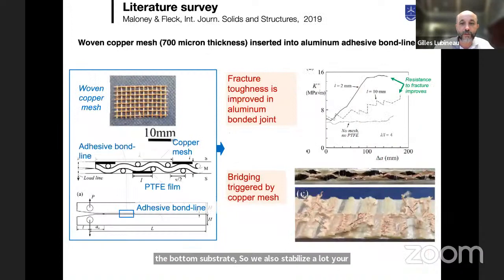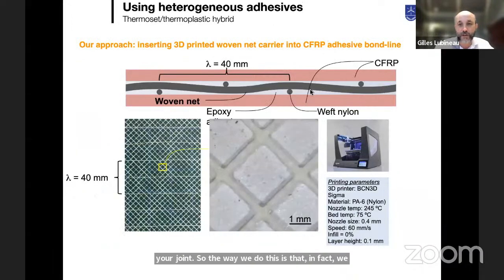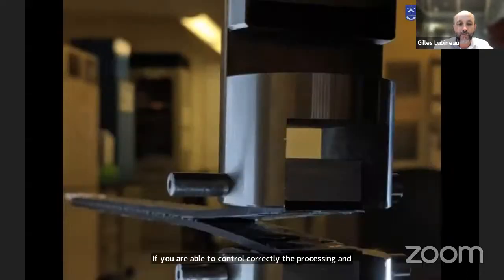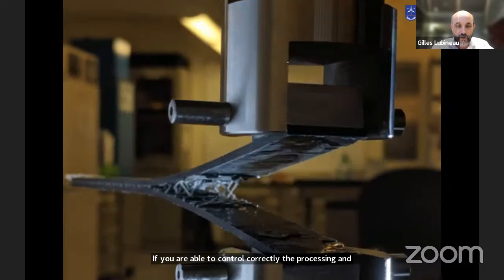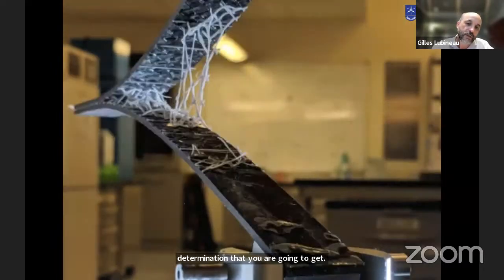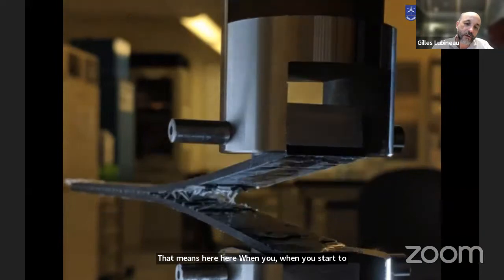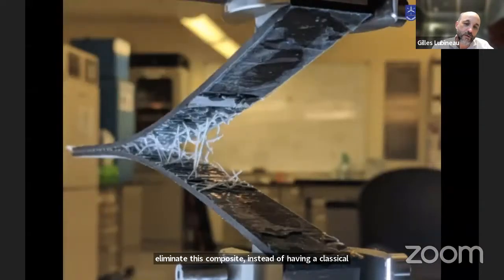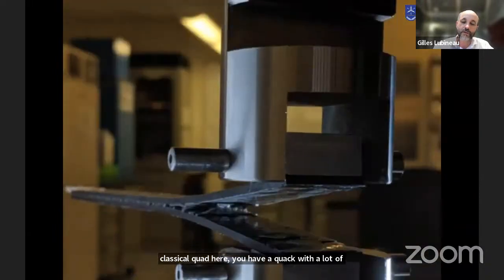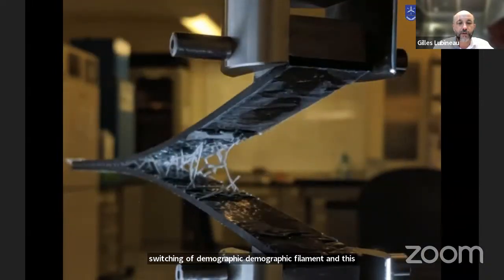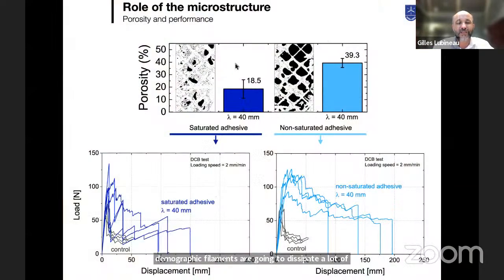So the way we do this is that we introduce, within the adhesive layer, a 3D printed thermoplastic net that is going to be inside the epoxy layer. And what is important, if you are able to control correctly the processing and the morphology of this film, this is the kind of delamination that you are going to get. That means when you start to delaminate this composite, instead of having a classical crack, here you have a crack with a lot of stretching of thermoplastic filaments, and these thermoplastic filaments are going to dissipate a lot of energy.